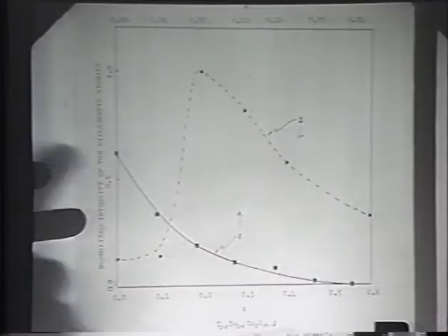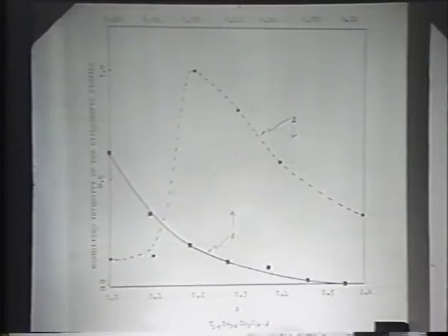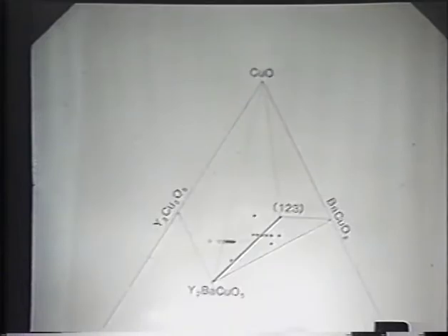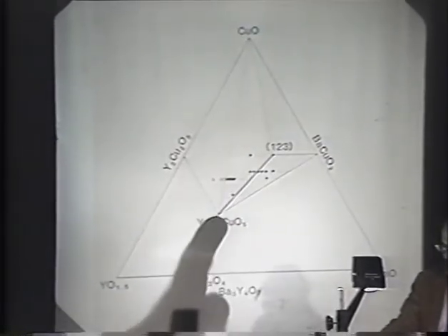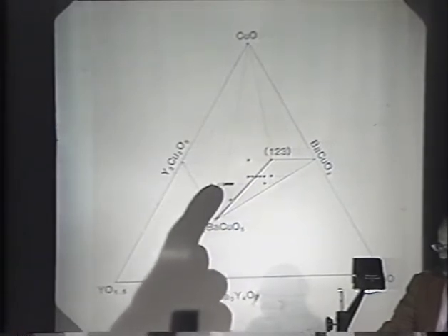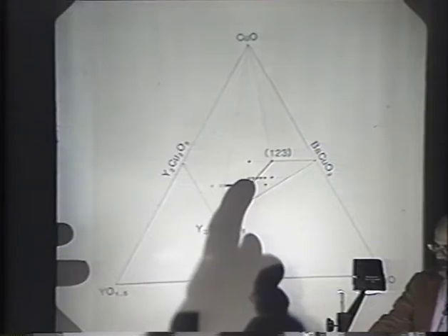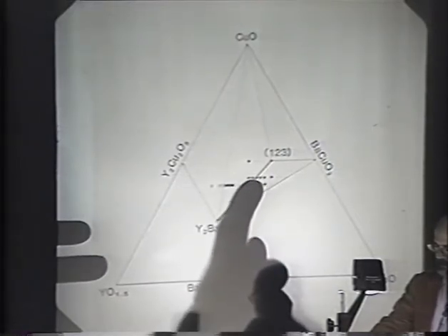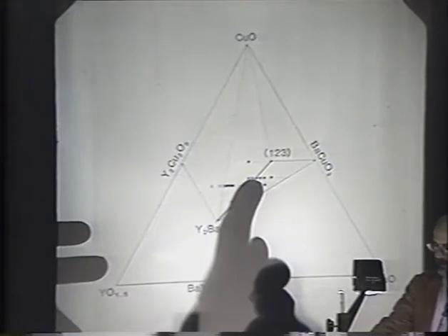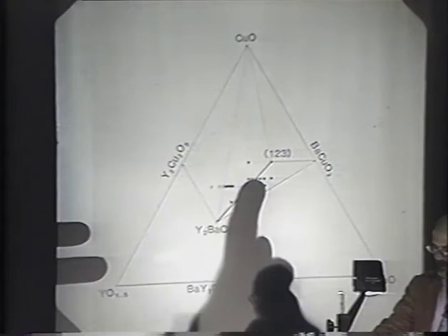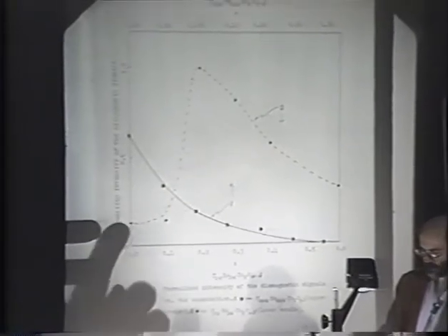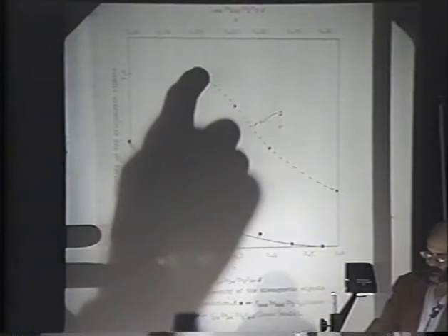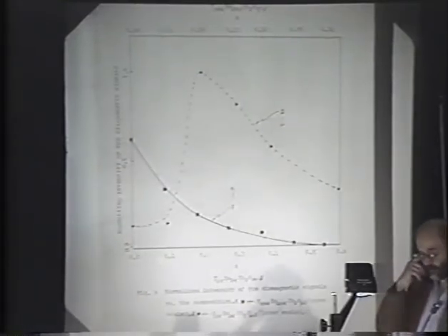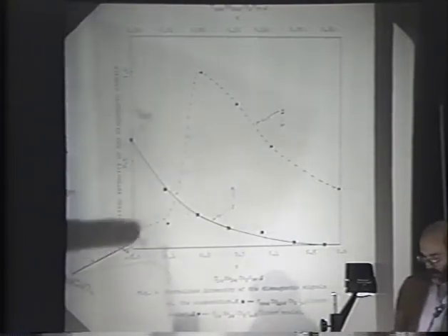Here is the normalized diamagnetic signal. There's nothing for the 3 points that would lie to the left of this, and then it drops off, and you can see the scatter is fairly minimal, so it looks like our composition control is reasonable. So some kind of join lies along here, and the phase to the left is not superconducting, the phase to the right is. This one should be superconducting right across, and by the phase rule there should be no difference between the amount of superconductor per point just to the left of this line and just to the right of this line. Unfortunately, we do see superconductivity right across there, as we should, but we do see a great big rise in the magnitude of the signal as we cross the line, which we should not see from the phase rule, if it is a perfect point compound.